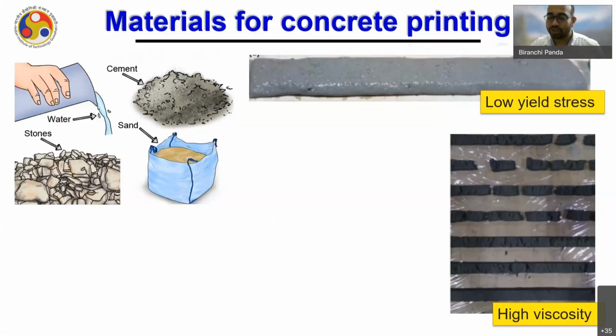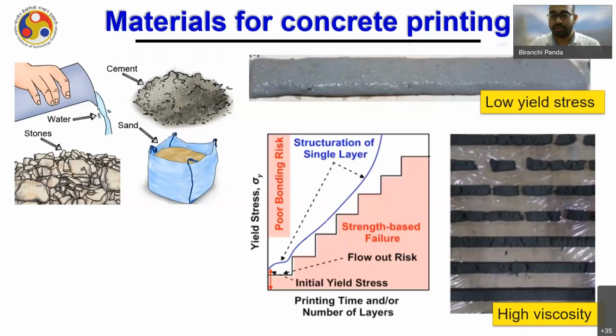So now let us talk about how we can improve this process. To improve this process, we need to maintain a minimum yield stress so that this material should not flow away, nor should it be discontinuous during printing. So we need a minimum yield stress for pumping, and also the same yield stress is going to be responsible for holding the shape as per the nozzle.